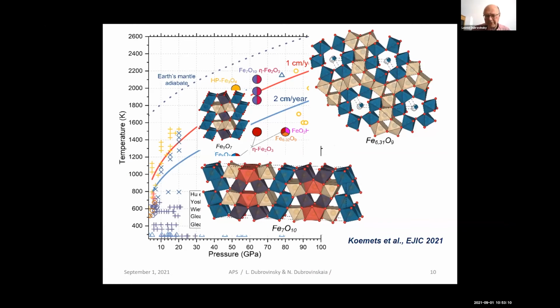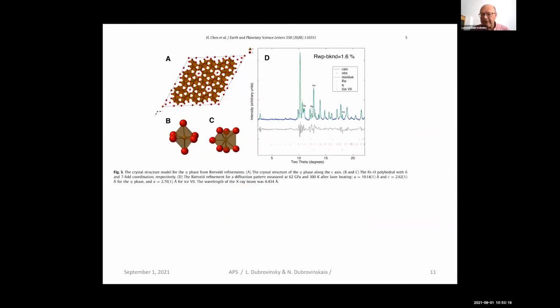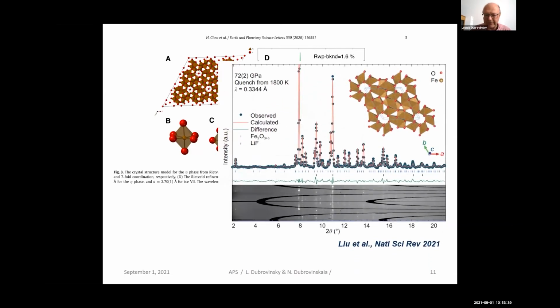In fact, this interesting phase deserves special consideration, probably a whole lecture for half an hour. I do not have this time, so just a couple of words. This phase was reported or observed in the experiments of different groups over the last, let's say, 1 or 2 years. In these publications there were different interpretations of this phase. Some people say that it is over-oxidized, not hydrogen, but an excess of oxygen. Some say that it is a hydrogen-bearing phase, and in these channels of the structure sits not only oxygen, but somewhere the hydrogen.